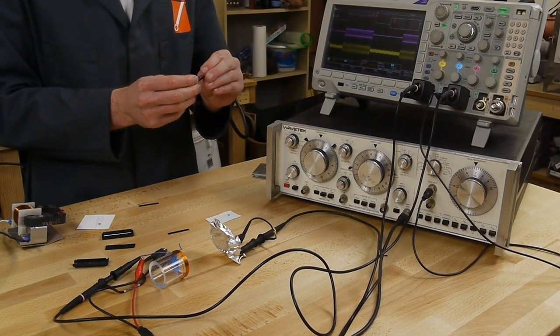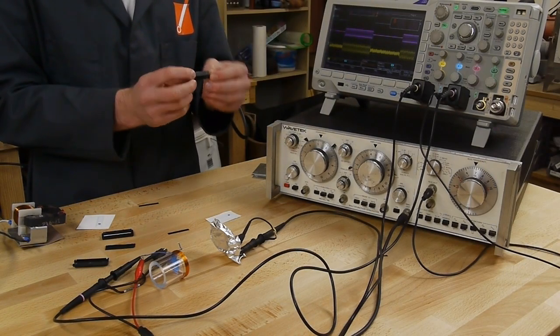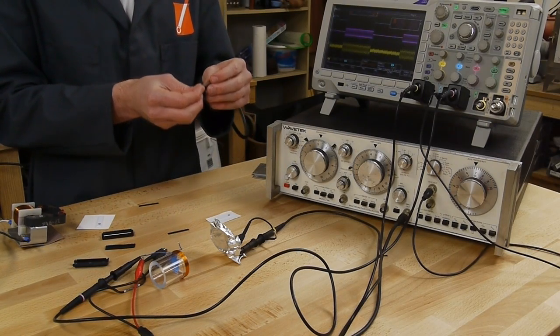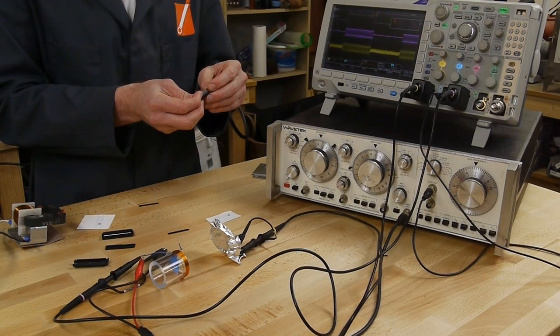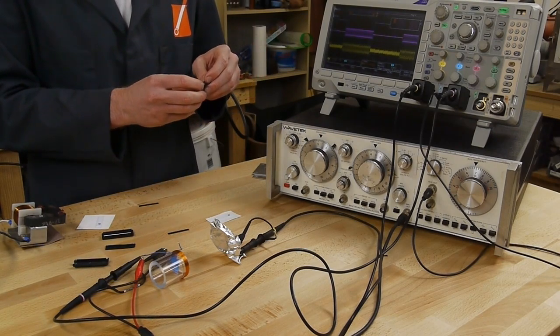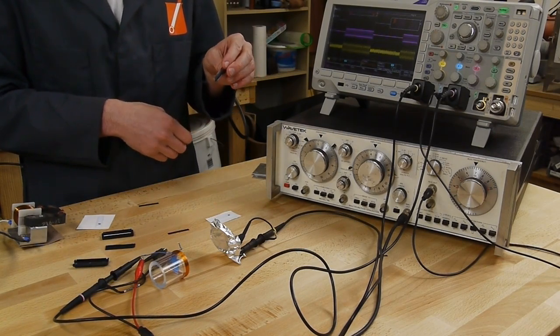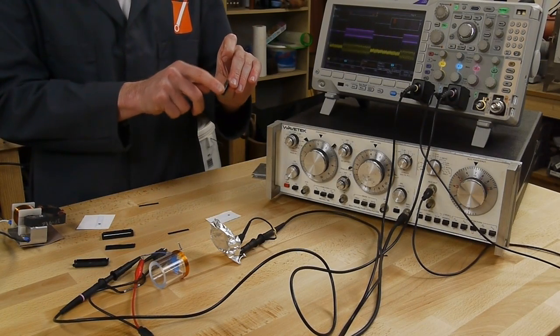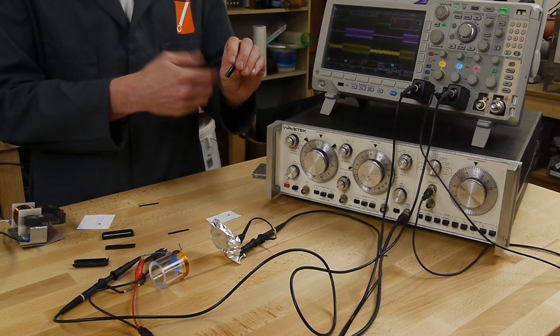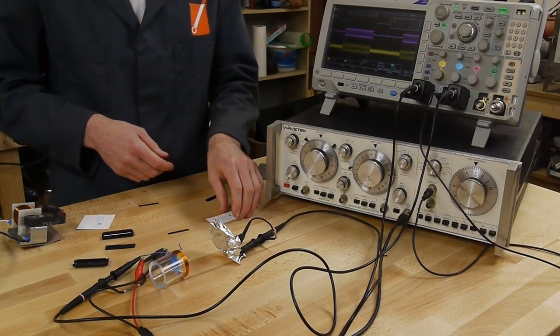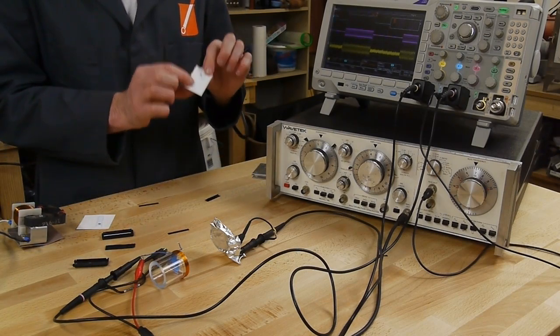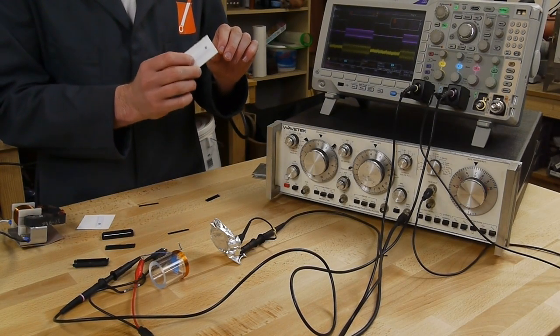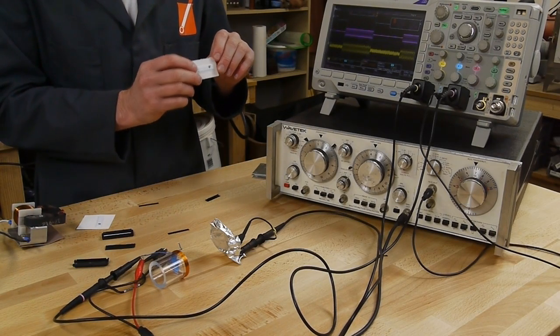The trick is that this little cheap magnet in here, it's basically just a thin strip of another iron compound. When it's magnetized, the strip is active because it's in that steep region of the slope of the response curve there. To activate a tag, you put a magnet near it which magnetizes this permanently, and then the tag is active. To deactivate one of these tags, you demagnetize the strip, then it's back down to that shallow area of the curve and it won't respond, it won't oscillate at 58 kilohertz.